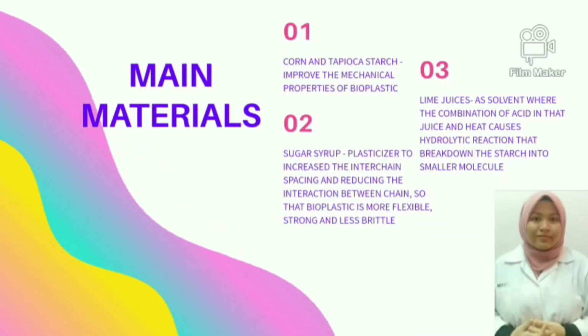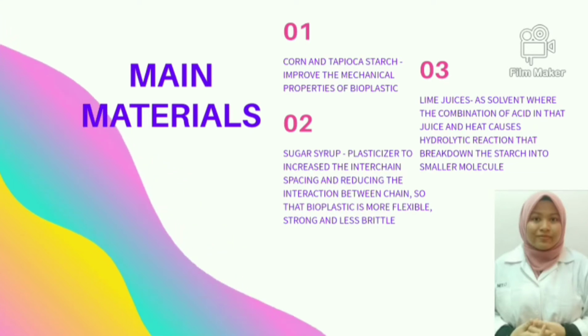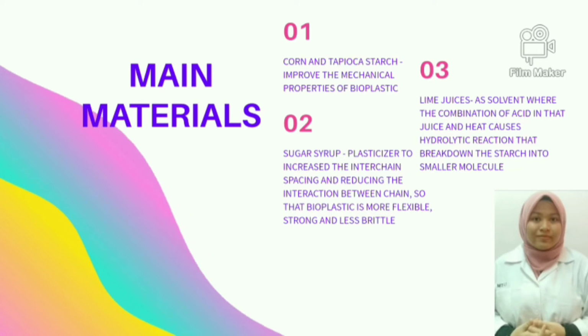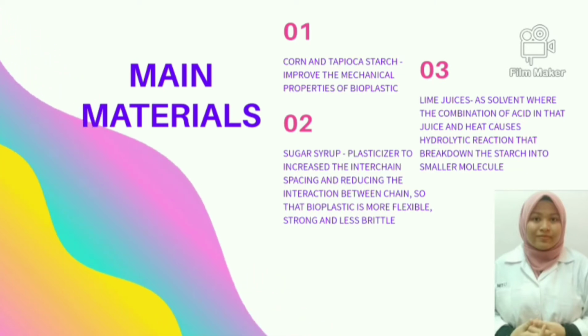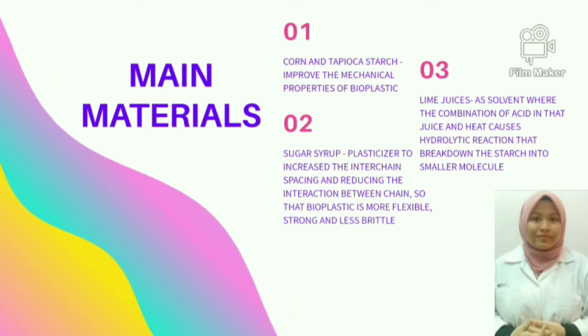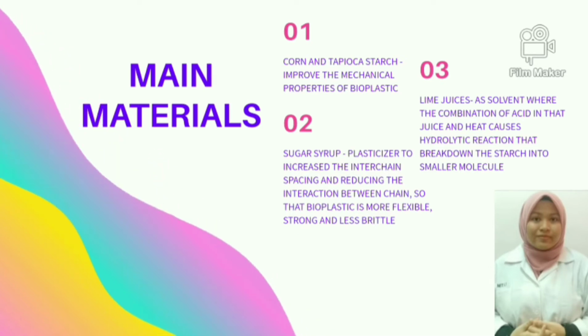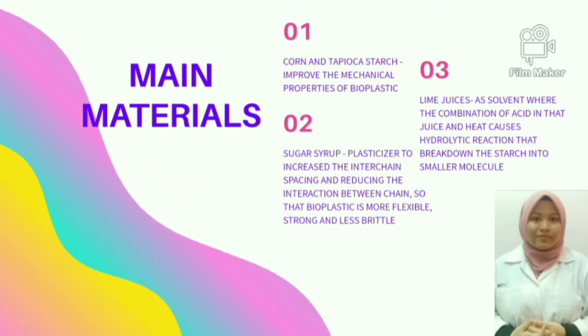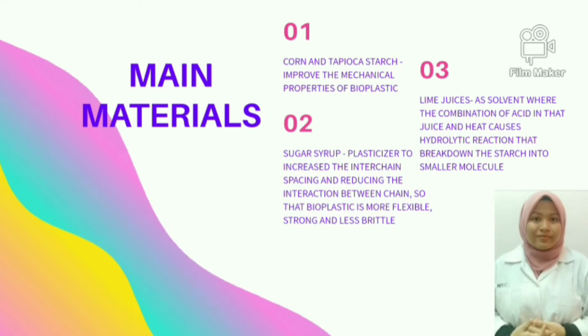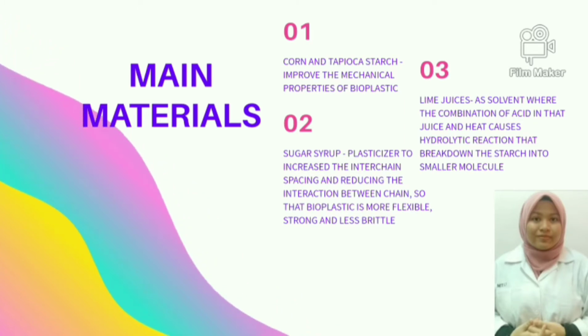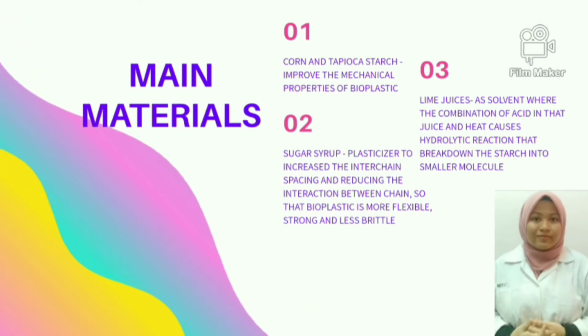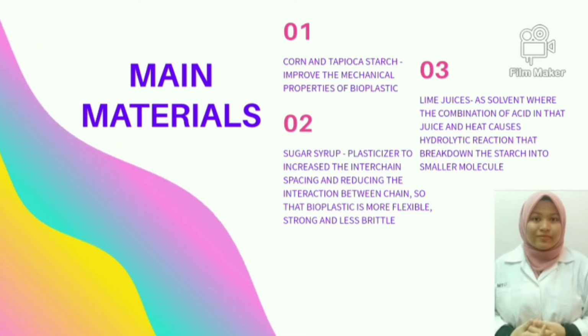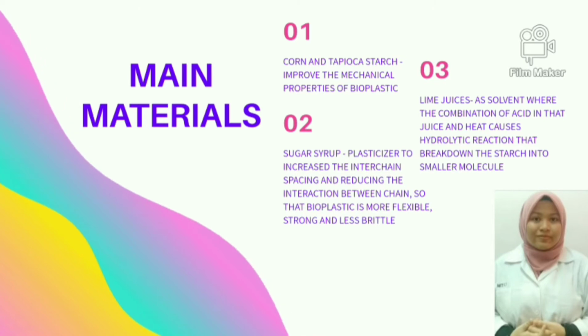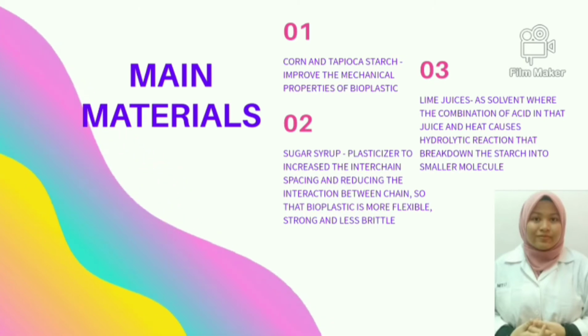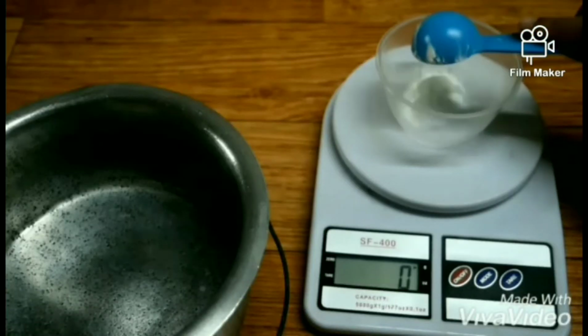The difference between our project and other studies is the main materials that we use. Firstly, we use a corn and tapioca starch blend, where we want to improve the mechanical properties of the bioplastic. Next, we replace glycerol with sugar syrup as the plasticizer to increase the interchain spacing and reduce the interaction between chains, so the bioplastic is more flexible, strong, and less brittle. We use lime juice instead of vinegar. The combination of acid in the juice and heat causes a hydrolytic reaction that breaks down the starch into smaller molecules. This combination has never been done before by any researcher.